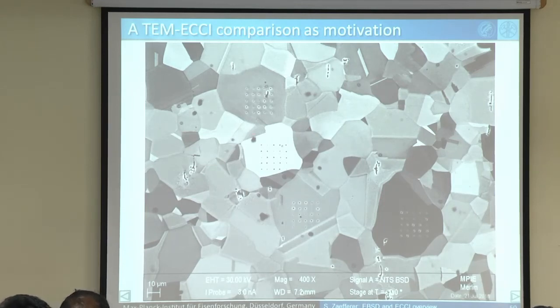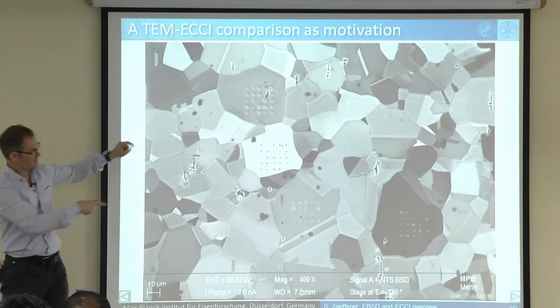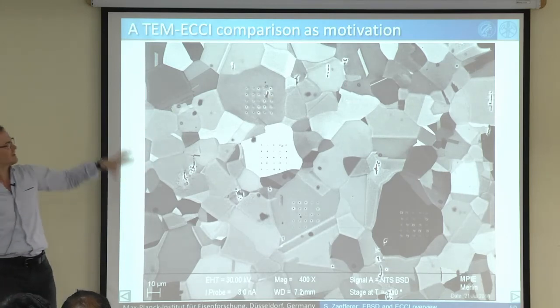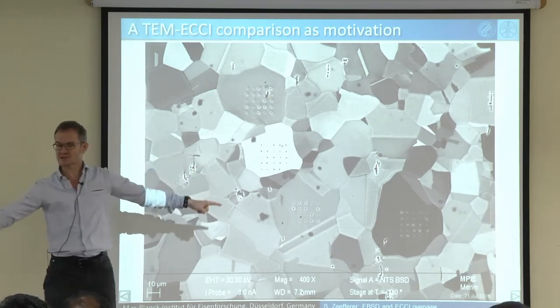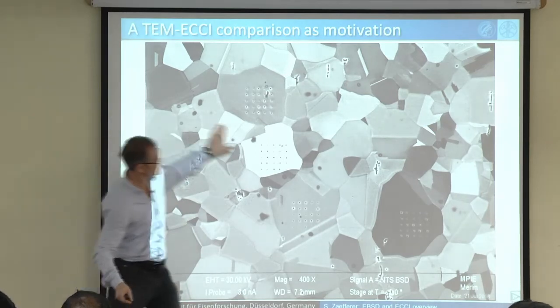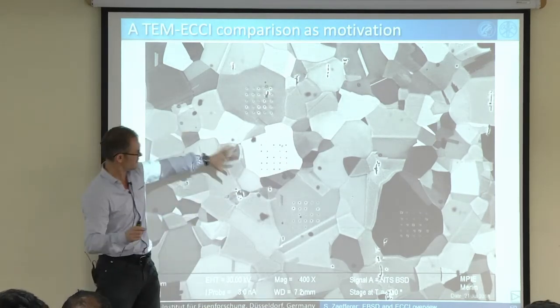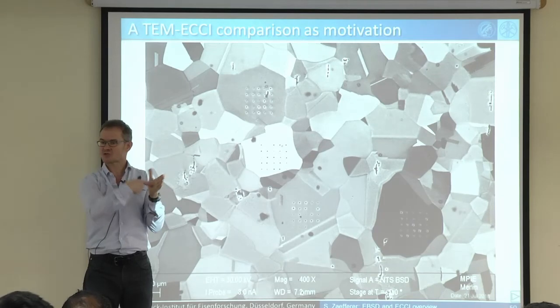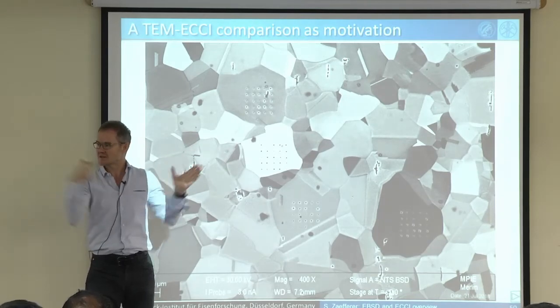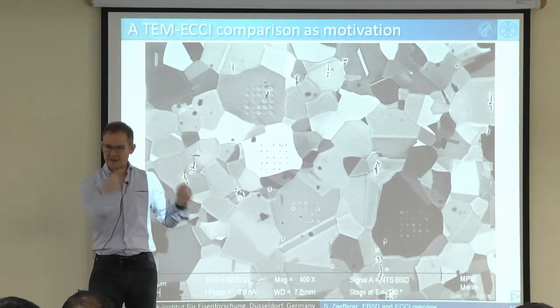I could go to a grain boundary and do it there and see how dislocations transmit into the neighboring grain. But what I did here is I took these indents into 20, 30 grains. Then I took all these pictures. Then I polished the sample very lightly to remove all these indents. I charged the sample with hydrogen, and I indented the same grains again. It's exactly the same grains, and I compared.